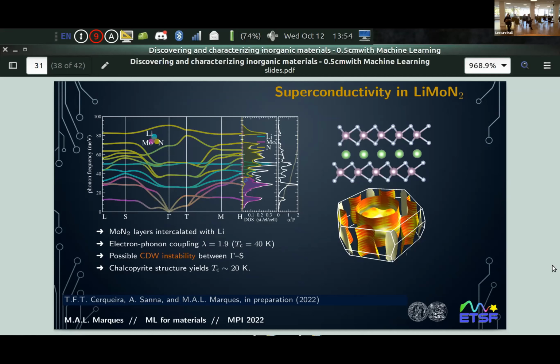This material is actually an experimental material. It was synthesized already a long time ago, searching for superconductivity. But theorists immediately did band structure calculations and realized that the Fermi surface, I'm sorry, that is here, is not two-dimensional. There is this part here that is not two-dimensional. So they said, not interesting for superconductivity. This is our calculation, gives 40 Kelvin. So apparently being two-dimensional is completely irrelevant.